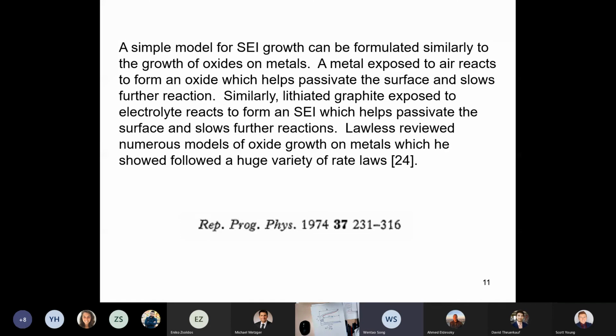So for the additive that is used in the previous slide, like the sulfur-containing additive, when they form the SEI, does all the LEDC change? Is the SEI on graphite solely formed by this additive, or is there still some EC involved in this formation process? Yeah, it depends, right? We talk about additives that dominate the SEI composition, and then we talk about SEI modifiers that modify it a little bit. So there's two different types of things that happen.